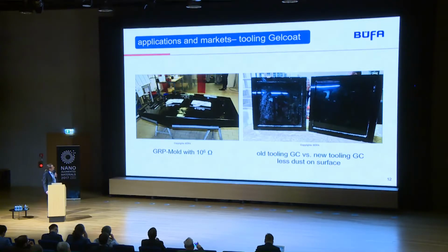Yeah, these are pictures from the mold on the left side. You can also see it live in the lobby. And on the right side, we make a test between the standard tooling Gelcoat and the new one. And these are 2 small molds. We demold the part, and after demolding, we throw a little bit of dust, or in this case, a handful of flour to the surface.